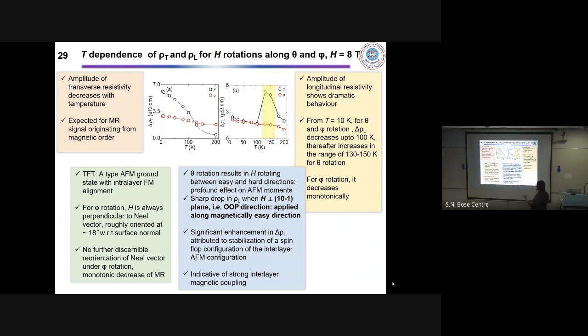And we have seen there is a sharp drop in rho L when the H is in the out of plane direction, that is applied along the magnetically easy direction, in case of the MR data also. So there is a significant enhancement in delta rho L, and this can be attributed to stabilization of the spin-flop configuration of the interlayer antiferromagnetic configuration, and the study also indicates that there exists a strong interlayer magnetic